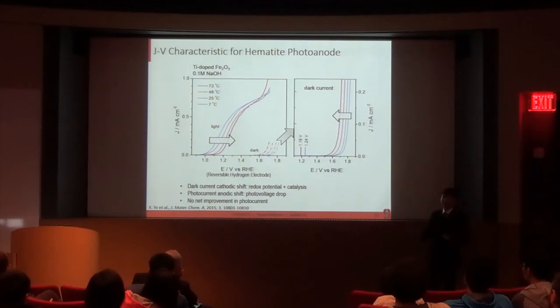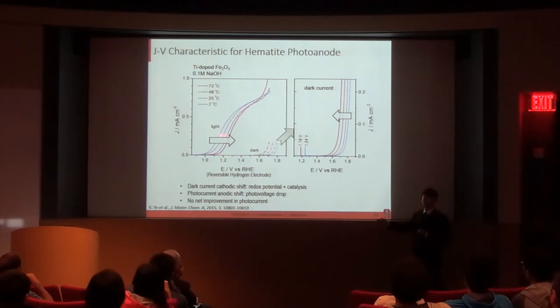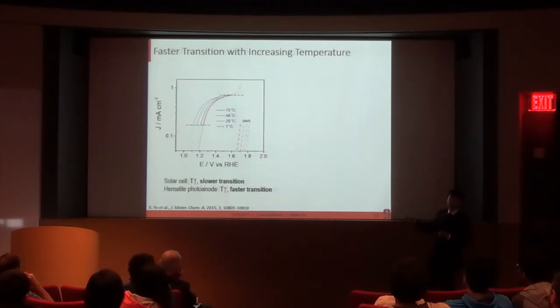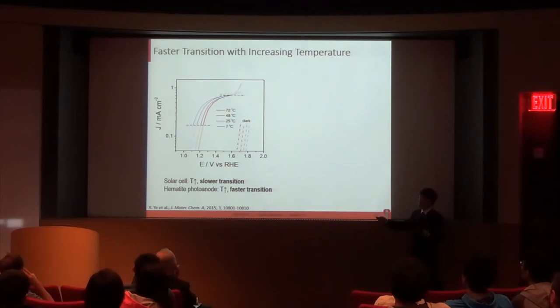However, there's no net improvement in the photocurrent. So you may immediately conclude that increasing temperature is bad for hematite photoanode. But wait a minute. As I look closer to this JV plot, we actually can see a hint of thermal enhancement. You can see that the photocurrent at higher temperatures seems to arise faster and can eventually catch up with the photocurrent at lower temperatures. This can be viewed more obviously in this semi-log plot, that the photocurrent at higher temperatures exhibits a faster transition from the reaction limiting regime to the saturation regime.